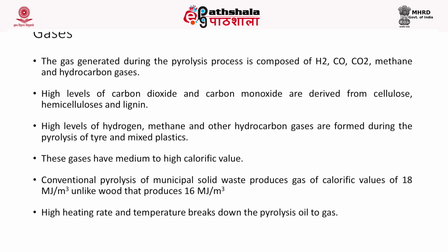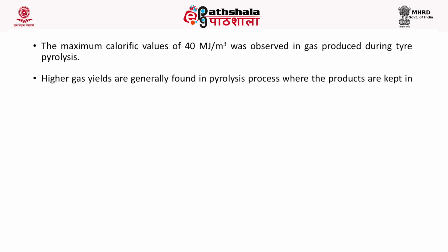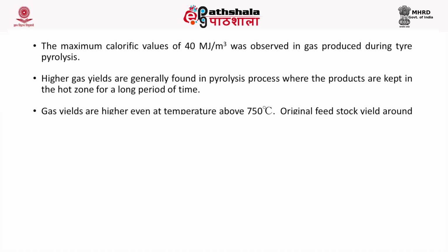Now the conventional pyrolysis of municipal solid waste produces a gas of calorific value of about 18 megajoules per meter cube when compared to wood that produces 16 megajoules per meter cube. Now, high heating rate and temperature breaks down the products or the pyrolysis oil into gas. So, the maximum calorific value is found during tire pyrolysis, which results in a calorific value of 40 megajoules per meter cube. Also, higher gas yields are generally produced when they are kept in a hot zone for a long period of time. Generally, the gas yields are very high at a temperature above 750 degrees Celsius, and the gas generation will be around 70% at this temperature.